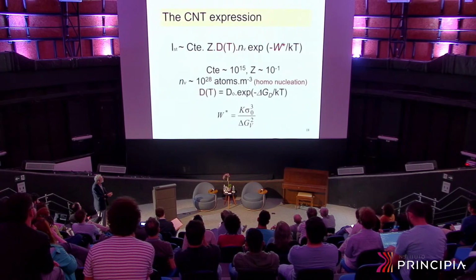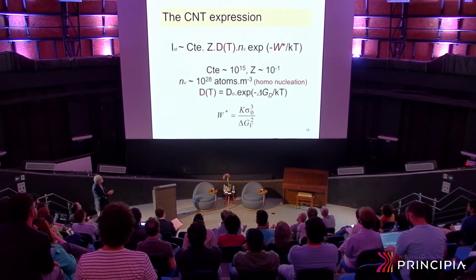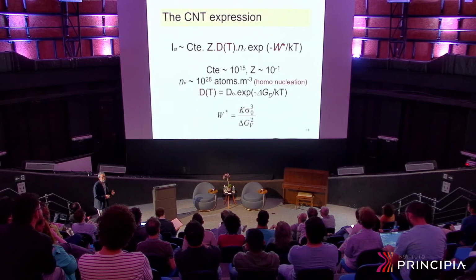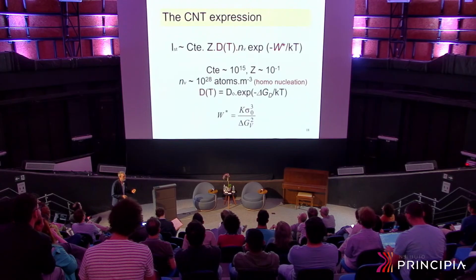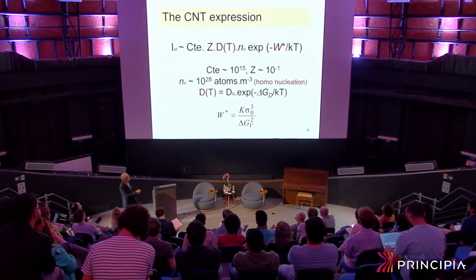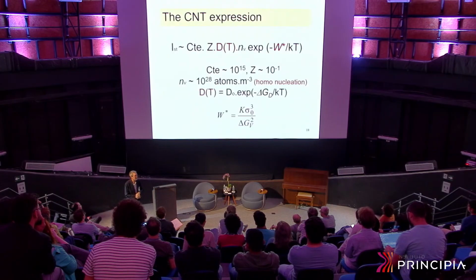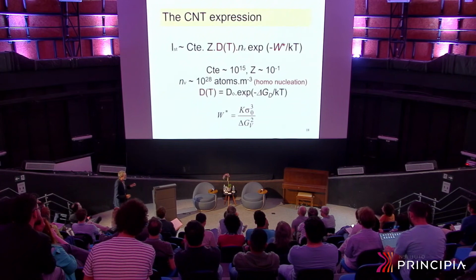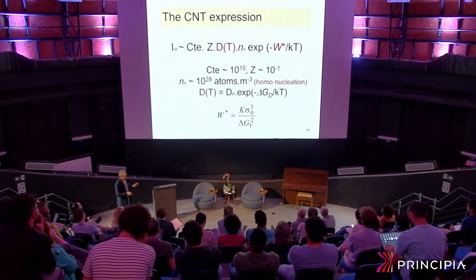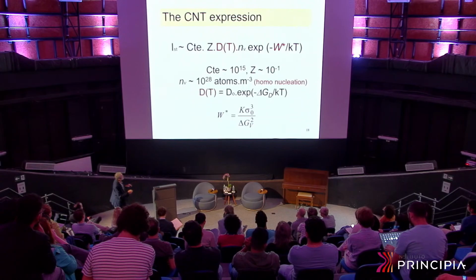If you can measure independently this quantity here and this quantity here, you could then calculate nucleation rates and compare with the experimental data. Unfortunately, we cannot measure the interfacial energy. There's this unknown parameter, which is very annoying. So the best we can do is to fit, say, this equation to nucleation rate data for some systems, and then leave sigma as a fitting parameter. But it will get better towards the end of my talk.